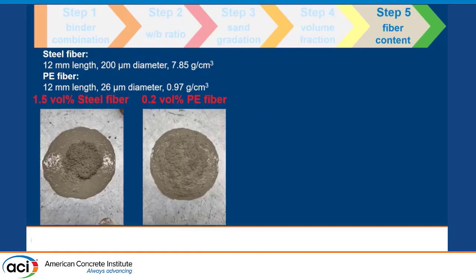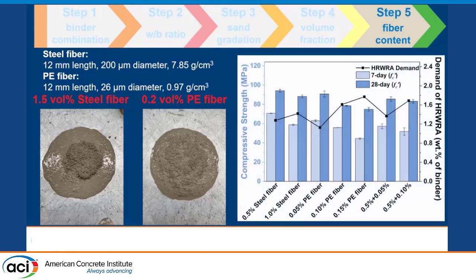So here's the final step. Here is some basic information on the steel fiber and PE fiber that we used in our study. The first thing we try to do is to determine the upper limit of the fiber content. As you can see, the upper limit is 1.5% by volume for the steel fiber and 0.2% by volume for PE fiber. So here are the results. We also did the tests of 28-day and 7-day compressive strength and the demand of high range water reducer in the mixture.